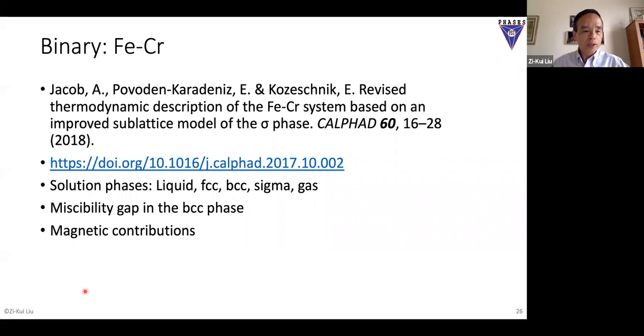And this one's done in 2018. I know that Brandy in my group is finishing another one, the newest one, will be 2020. So this one you have solution phases - liquid, FCC, BCC, and another phase, sigma phase. That's a very complex phase, okay? You have gas phase, of course. You have a miscibility gap in the BCC phase. You have magnetic contributions in the BCC and the FCC.